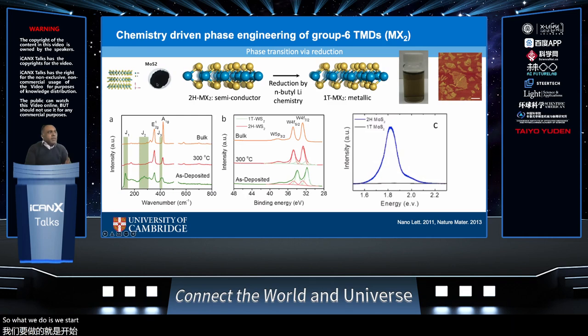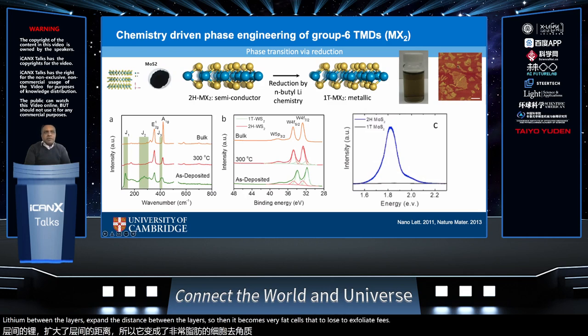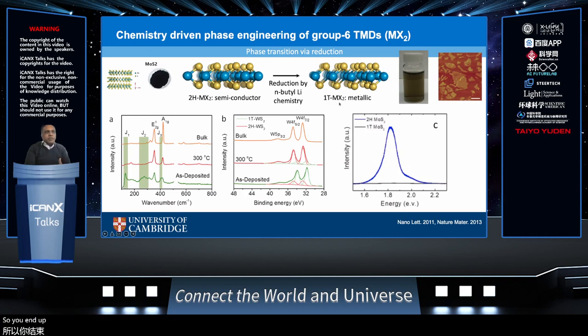What we do is we start with molybdenum disulfide powder, and we reduce the MoS2 by n-butyllithium. This n-butyllithium chemistry leads to charge transfer to the MoS2, and this additional electron in the d orbital of molybdenum drives the phase transformation from the 2H to 1T. In addition to the phase transformation, the intercalation of the lithium between the layers expands the distance between the layers, so it becomes very facile to exfoliate these TMDCs into individual sheets, as shown here. What you end up with after this reaction is lots of single layer metallic phase MoS2 sheets that can be dispersed quite easily in water or other solvents. And the phase transformation is characterized by features in the Raman.